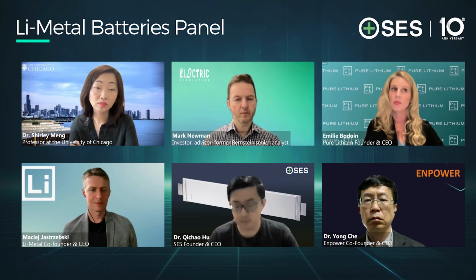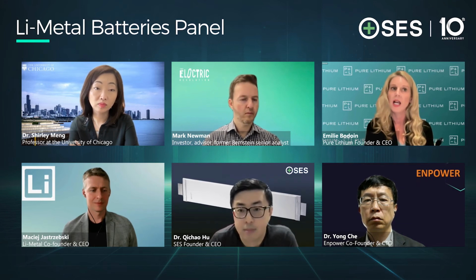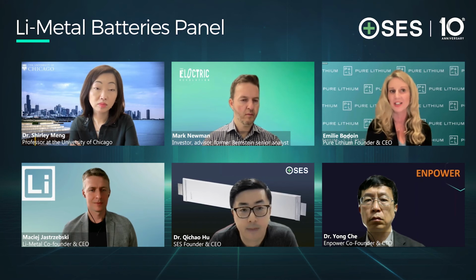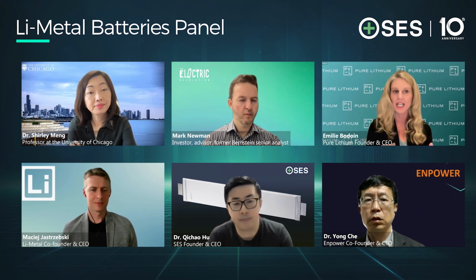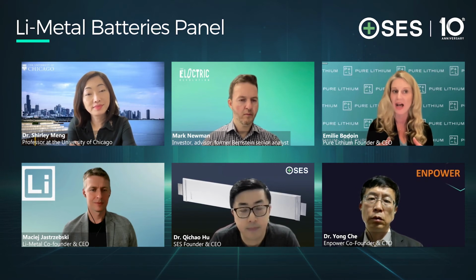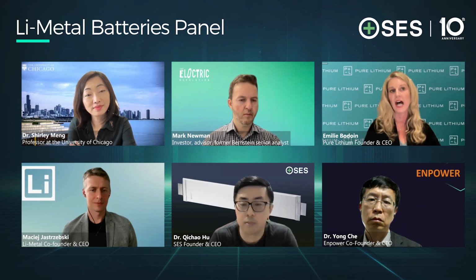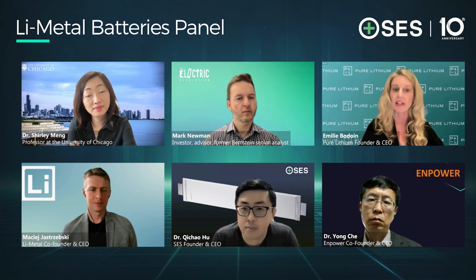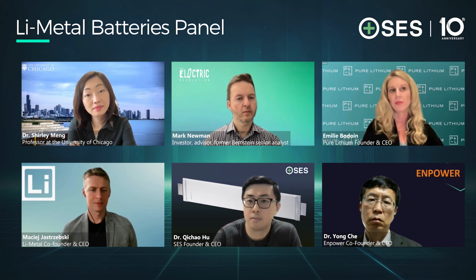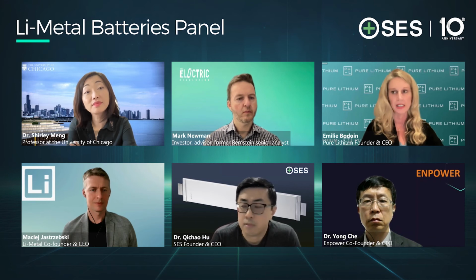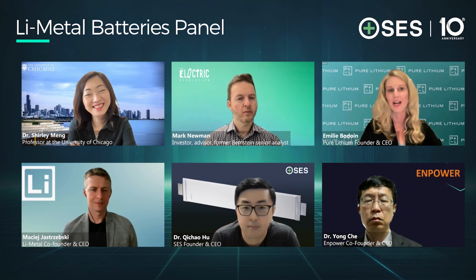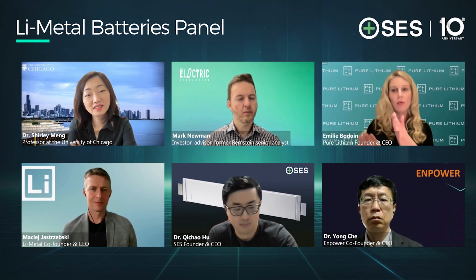And electrodeposition, for people who don't know, is a very well-known method to produce in situ metal coatings by the action of an electric current on a conductive material that is immersed in a solution containing the salt of the metal to be deposited. So take a bath, right? A lithium sulfate aqueous bath. Take a substrate, it's in that bath, and we have tricks that we do with that substrate. We've invented a novel polymer coating that acts quite like a leveling agent. Thus far, we've made films that are 80 by 110 millimeters, and that's not large enough for the large format that Qichao is going to need, but we're working on it. We're only a year and a half old. And we coat our copper with this polymer.